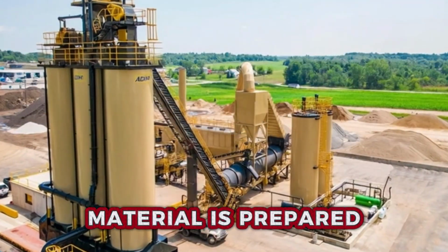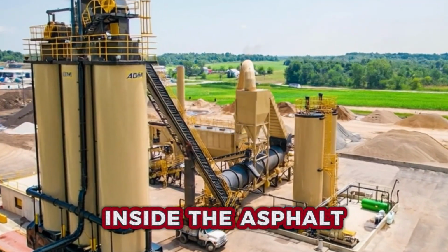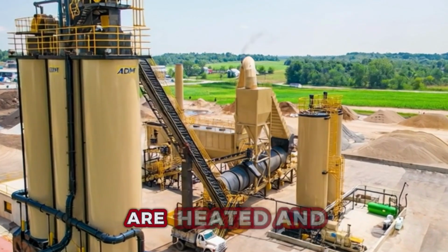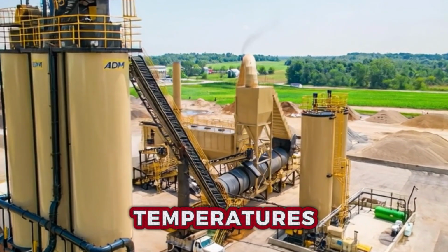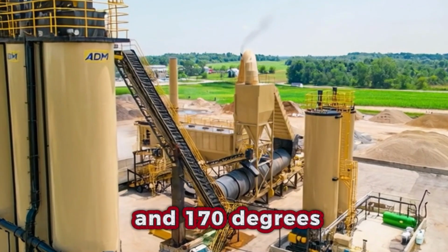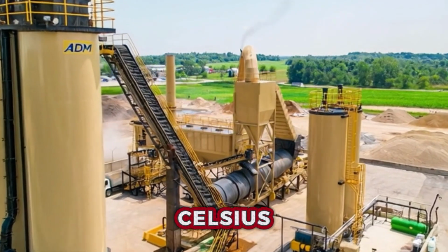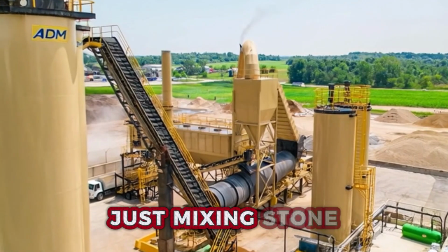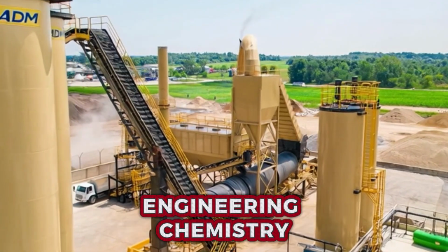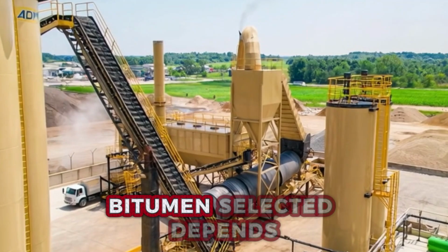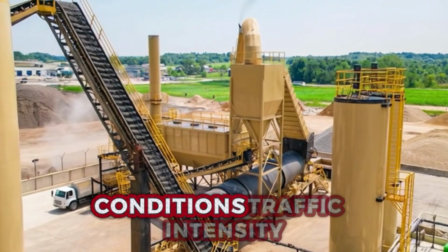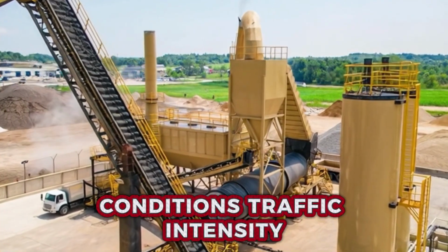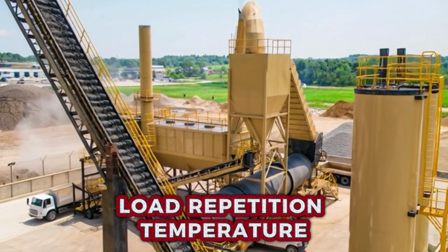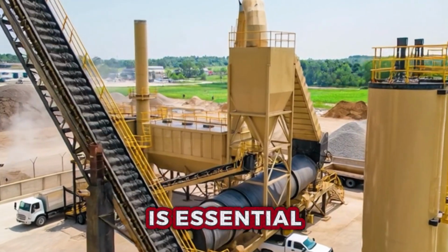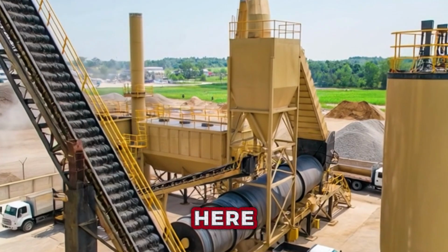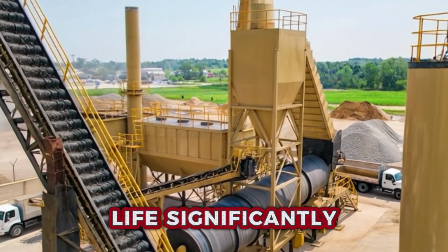Now the surface material is prepared. Inside the asphalt plant, aggregates and bitumen are heated and mixed at precise temperatures, typically between 150 and 170 degrees Celsius. This is not just mixing stone and oil, it is controlled engineering chemistry. The type of bitumen selected depends on climate conditions, traffic intensity, load repetition. Temperature consistency during mixing is essential, because small deviations here can shorten pavement life significantly.